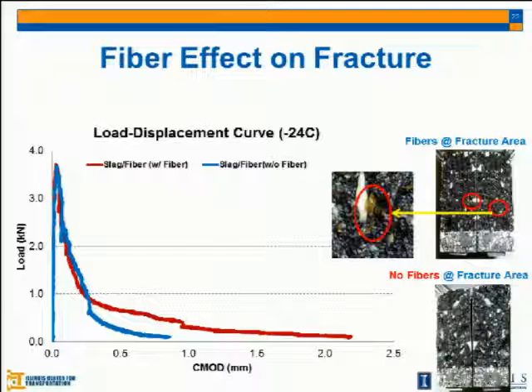But we noticed this fiber slag mixture has a very high COV of the fracture test result. So we took a look at the fractured face. Some specimens showed the fiber along the crack propagation area, but some did not. So fracture energy in this mixture depends on whether fiber is located in the crack propagation area or not.